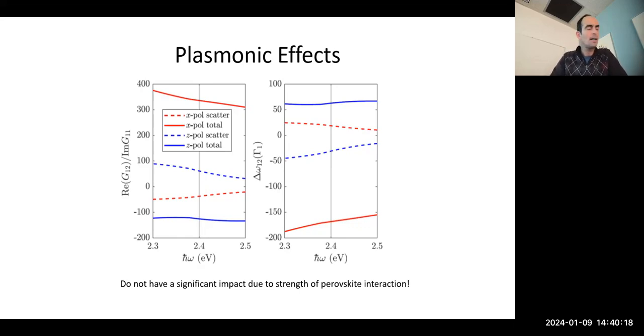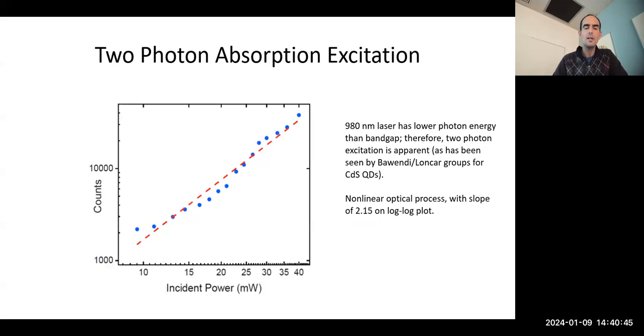We're not the only people discussing this effect. People in the solar cell community were interested in using these perovskite quantum dots to enhance the absorption of silicon materials, and they found the quantum dots would not talk to the silicon at all in the absorption - they just spoke to each other. So putting them on a silicon substrate had basically negligible impact.